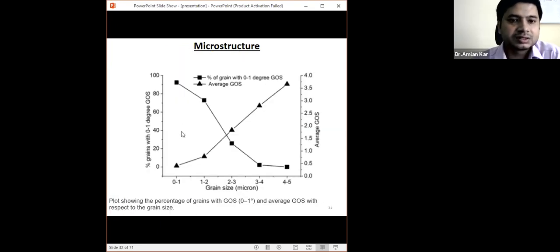This is just a representation of what we have seen. We can see here the grains corresponding to 0 to 1 degree of GOS. The grains with 0 to 1 degree of GOS are very, very high in the case of very fine grains, which have a grain size of 0 to 1 microns. These grains are actually the completely recrystallized grains.